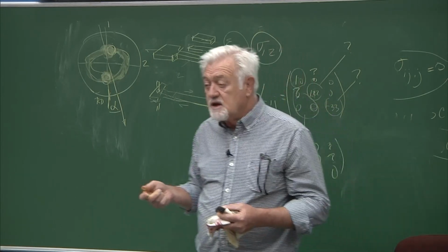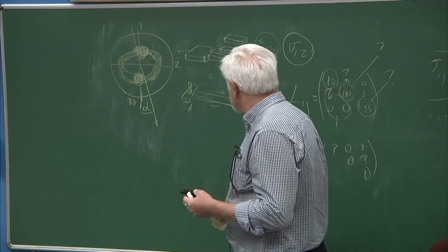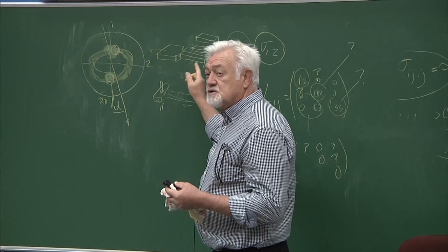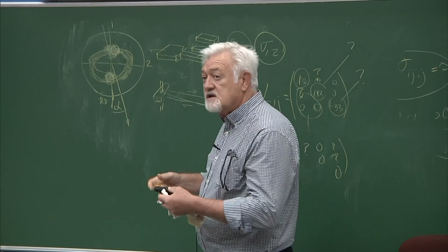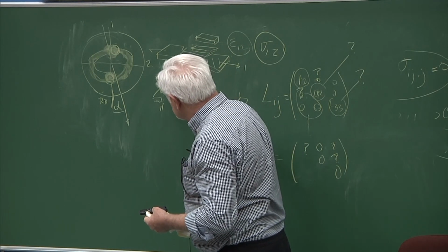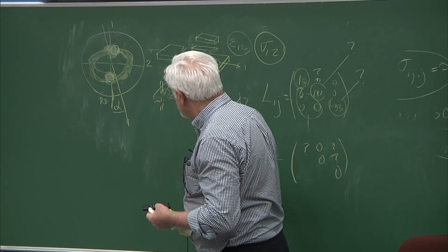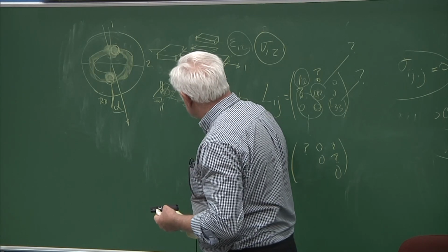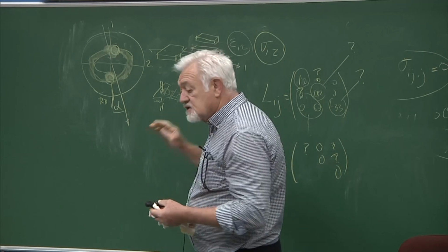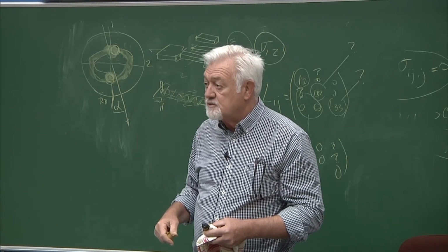So you can play with the boundary conditions. You can adapt the boundary conditions to the type of test that you are doing. If you have a very short gauge, then the shoulders will force it to remain parallelepipedic. If it is a very long gauge, once you are away from the shoulder, in all this region, it can shear. So those conditions you can kind of reproduce by changing the boundary value problem in the code.